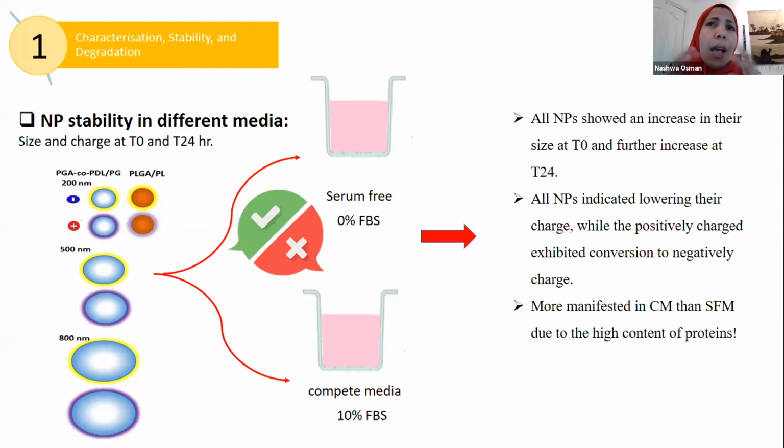you're adding a lot of these proteins to the medium, and this will make a corona, a layer around these nanoparticles that will change their size and charge. But this will help you later on as a researcher in understanding your experimentation and why you are getting the results, plus helping the readers later on to interpret some of the information. For example, to have some references, to have a bit of discussion for my results.